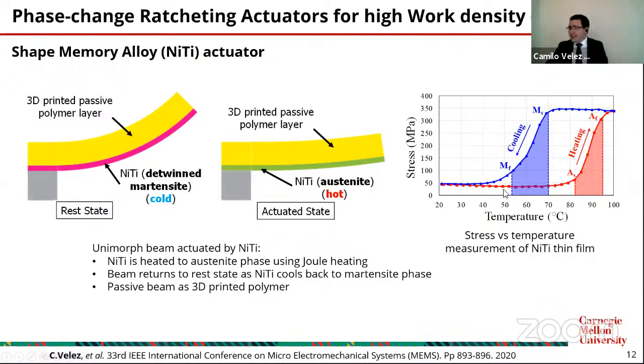When you increase the temperature of the material, there is a point where the material perceives a phase transformation, from martensite to austenite phase. During this phase transformation, there is a huge stress produced by this material. Whenever you cool down the material, the stress is relieved and it returns, but not in the same way.